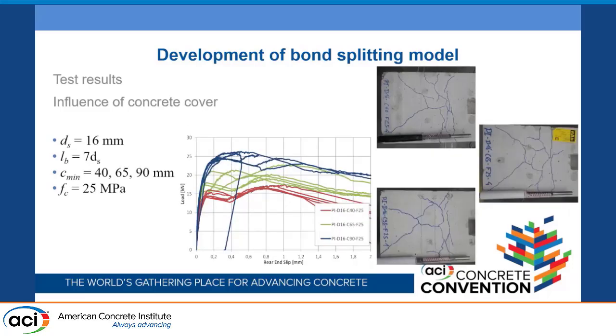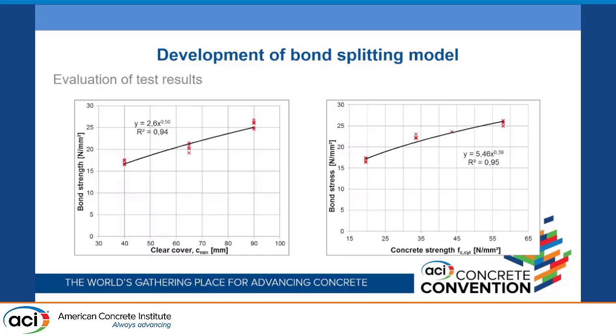The same thing if you increase the concrete cover from 40 to 65 to 90 millimeters. Again, we got an increase in the effective bond strength, or the splitting tensile strength. When we plotted them with these as the variables, so what's the bond strength with respect to the concrete cover or concrete strength, we got some trends.